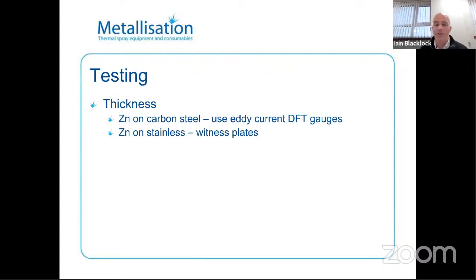So as far as testing goes, thickness can be checked with eddy current DFT gauges such as Positests, Elcometers, the same as what you'd use for dry film paint tests. If you're spraying onto stainless substrates, thickness can be checked with witness plates, but there's also some equipment that will read on stainless steel substrates as well, so you can get some readings.